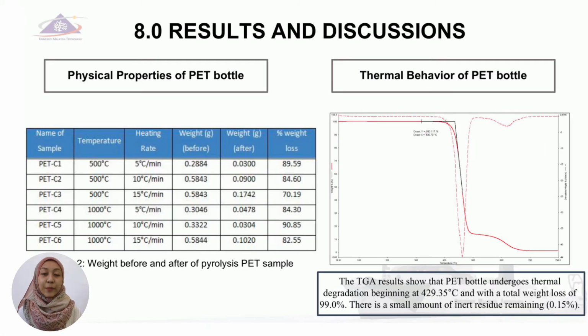For the result, the physical properties of PET bottle were recorded by observing the weight changes before and after pyrolysis. TGA analysis of the PET bottle justifies the percentage weight loss of the sample produced, as the TGA shows that PET bottle undergoes thermal degradation beginning at 429.35 degrees Celsius, and with a total weight loss of 99%, there is a small amount of inert residue remaining of 0.15%. So from the result analysis, 2 pyrolysis temperatures were selected, which are 500 degrees Celsius that acts as a starting point after thermal degradation begins, and 1000 degrees Celsius as the highest temperature due to the plateau of the TGA pattern that starts at 700 degrees Celsius.